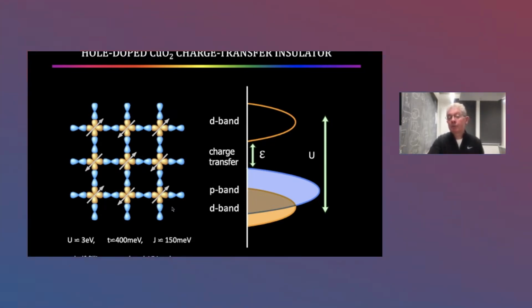And now if you represent that as a band structure shown on the right, the 3d9 band is at the bottom, the d band. It's separated from the empty upper d band by the Hubbard or Coulomb energy U, and that's a very big energy. But when Mother Nature was inventing this material, she put the oxygen p orbitals in between. So the energy level of the 2p6 oxygen p orbitals is much higher, and the energy splitting between the 2p6 orbital and the 3d9 orbital is called the charge transfer energy.